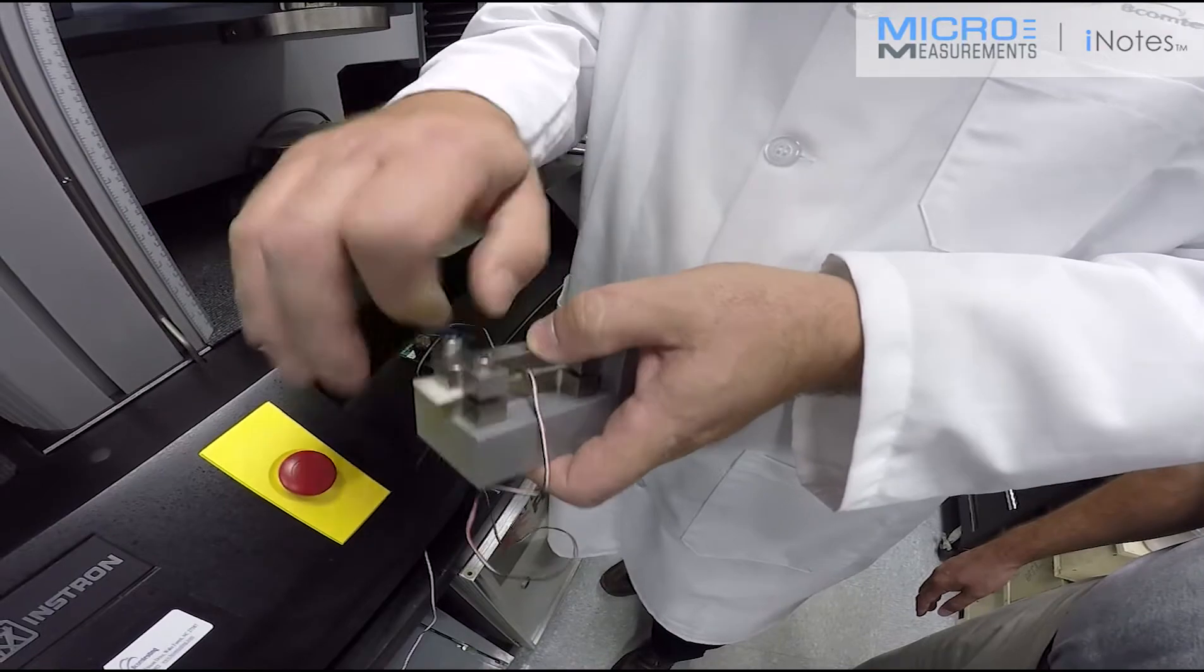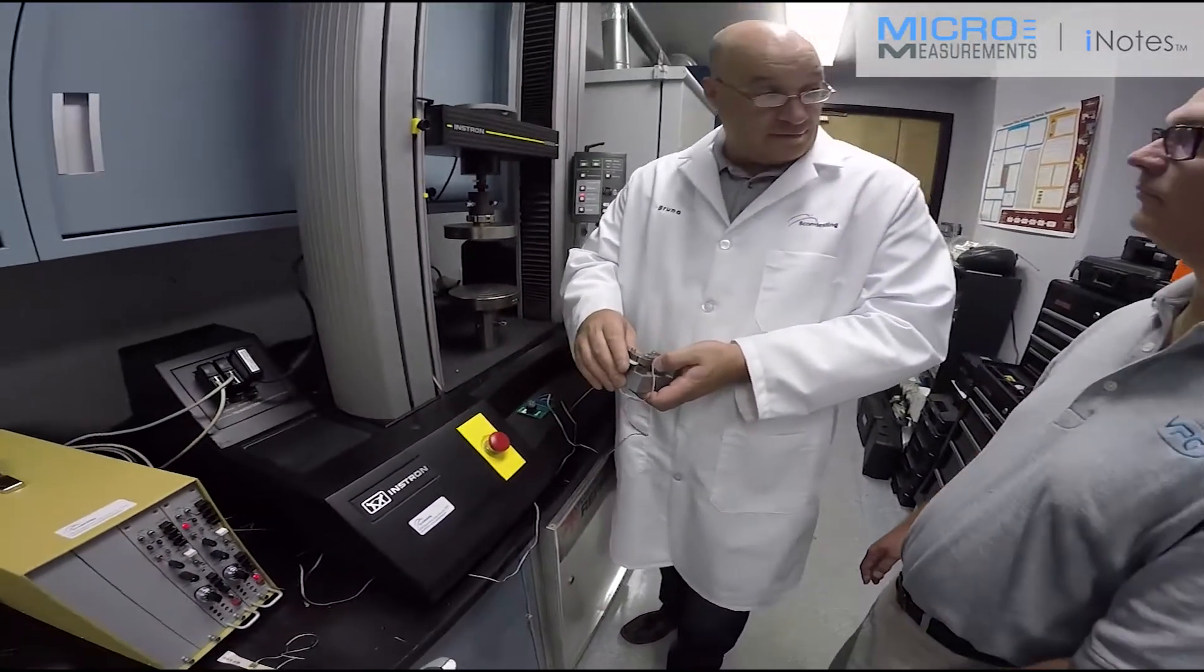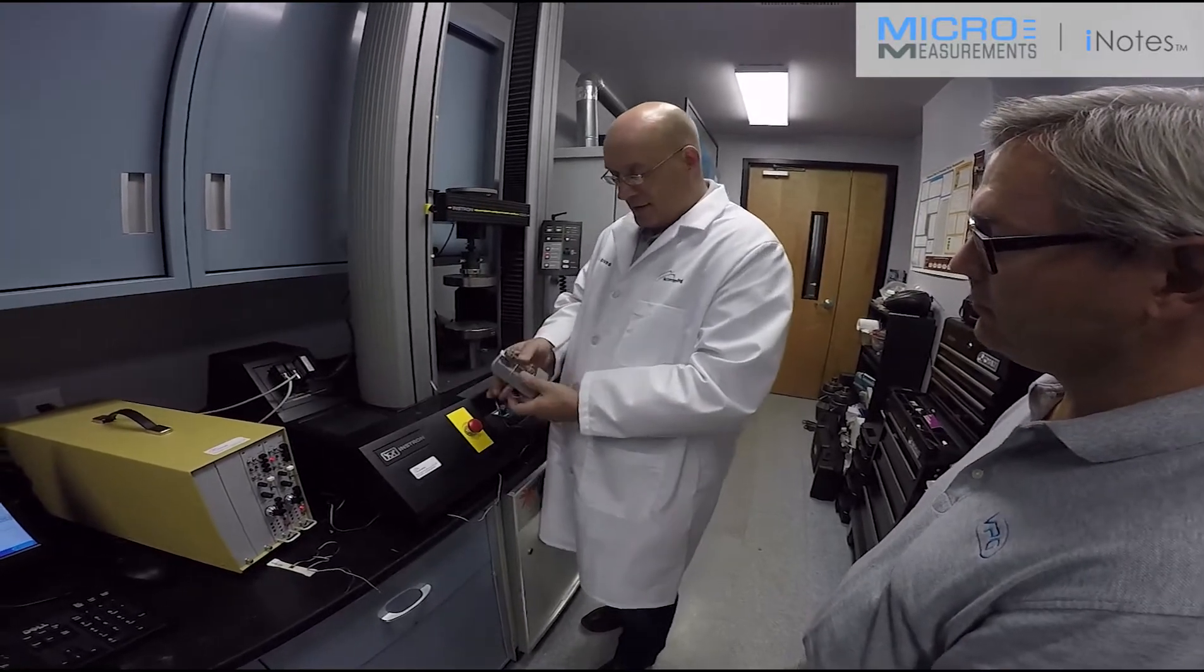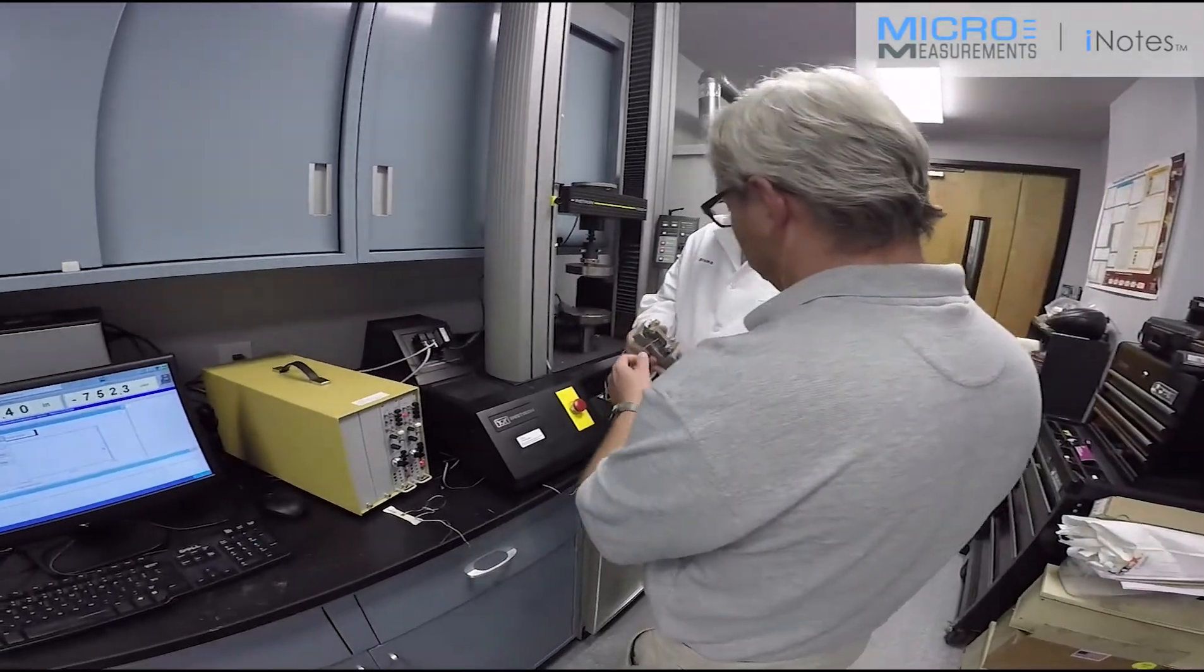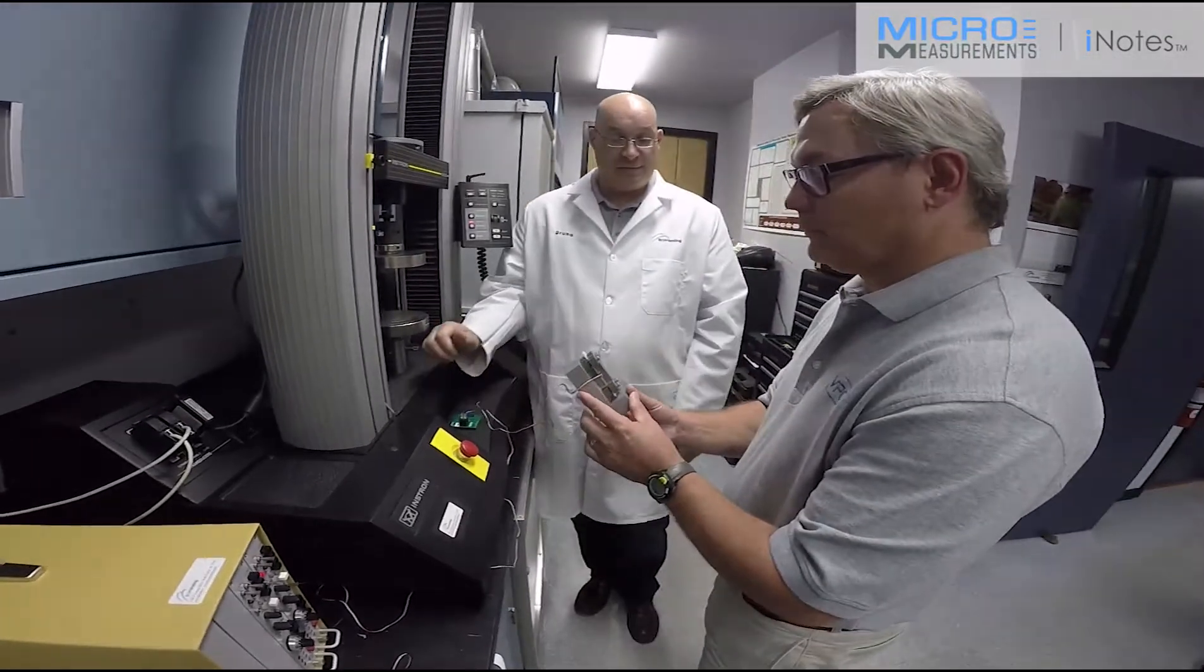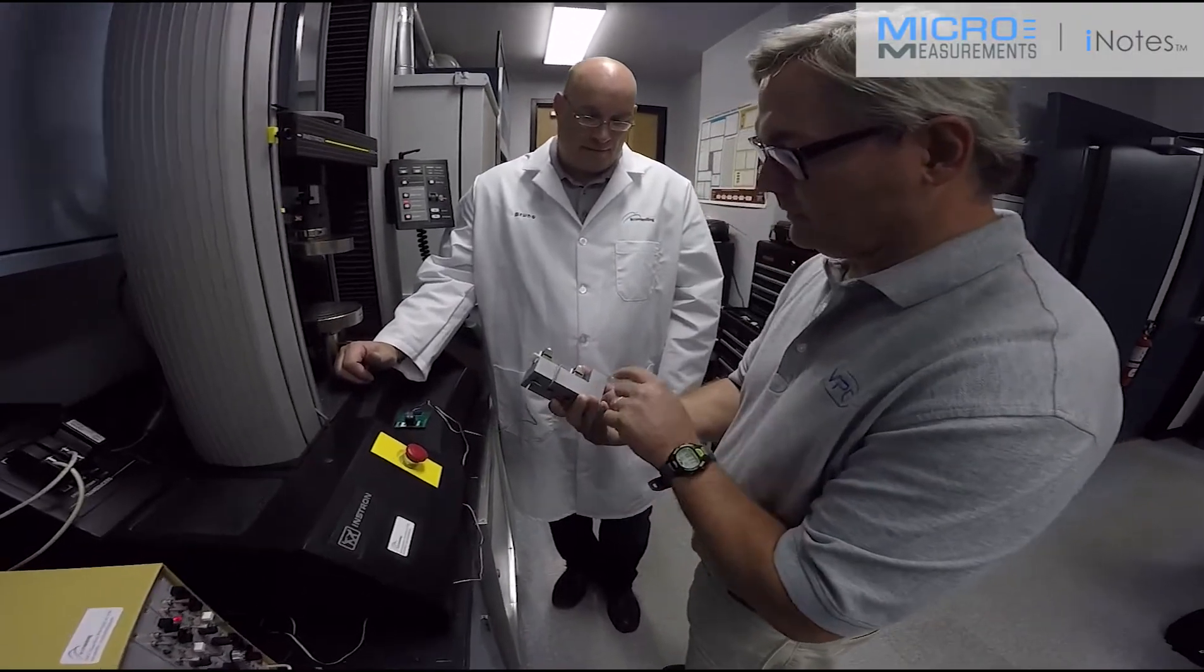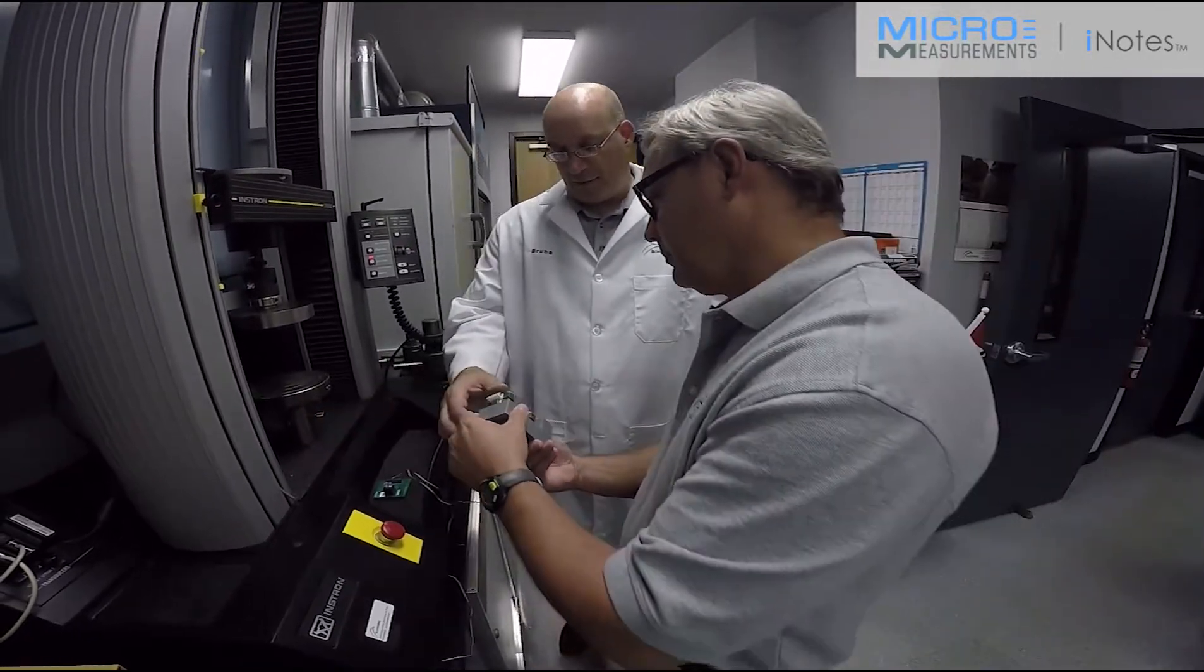In this case, I'm just going to hand-tight it. We're using a 2,000-pound frame for this test, which is not enough to take it to failure. We're not really interested in failure today. We're looking at modulus only. What we're going to do is hand-tight. We don't want to over-tighten this, because at that point, you might be more testing your ability to compress the specimen in the fixture versus actually running the specific test. So it gets loaded. This bottom portion of this L-shaped piece of metal loads the bottom, and the top gets loaded by the platen.